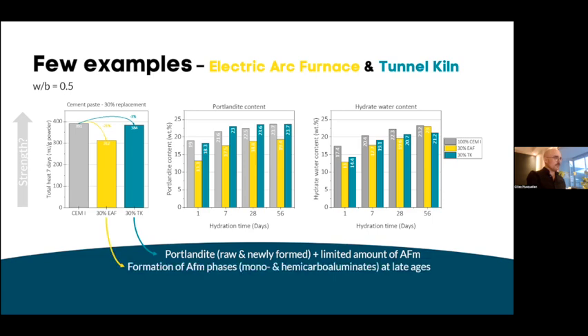For the other type of slag, it's mostly the formation of additional AFM phases that we have seen, and mostly at late ages, as we can see in the hydrated water content. Up to 28 days, the amount of hydrated water is significantly lower than for the reference. But at later ages, we actually completely catch up, which means it's a bit of a lazy guy, but it looks like it works.